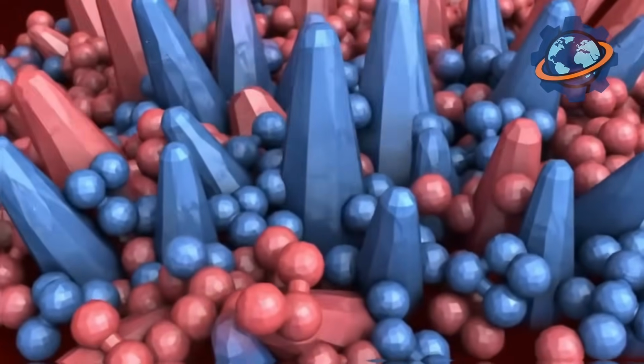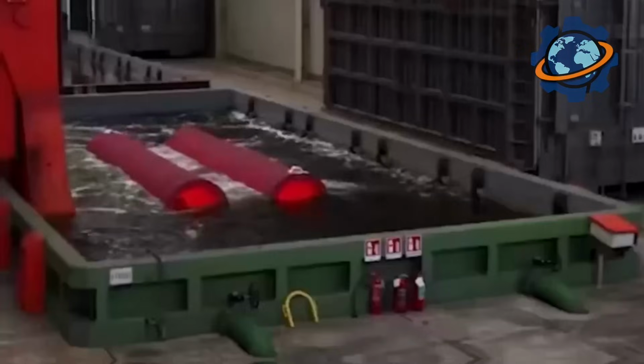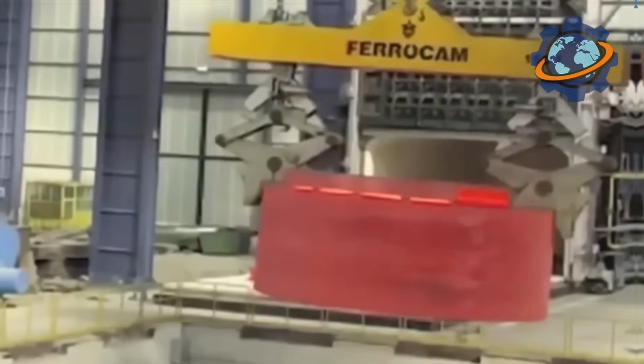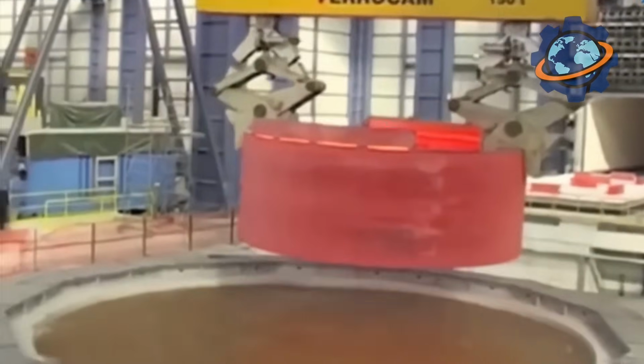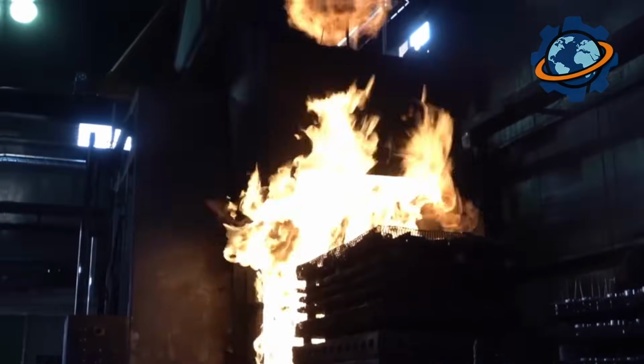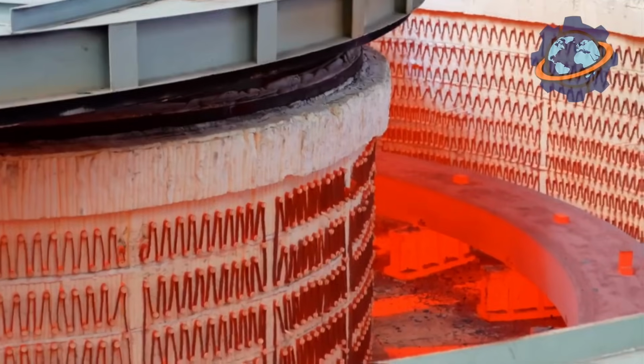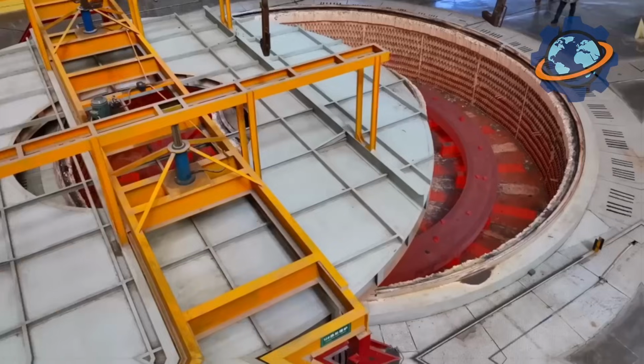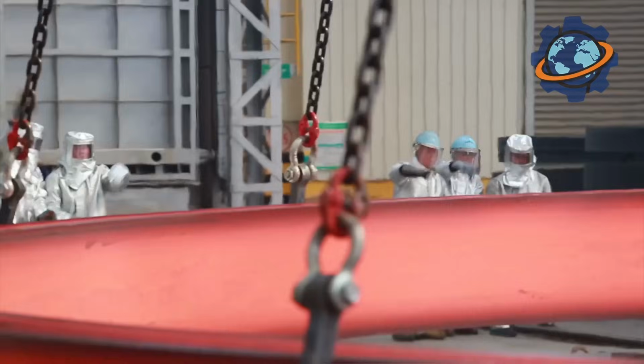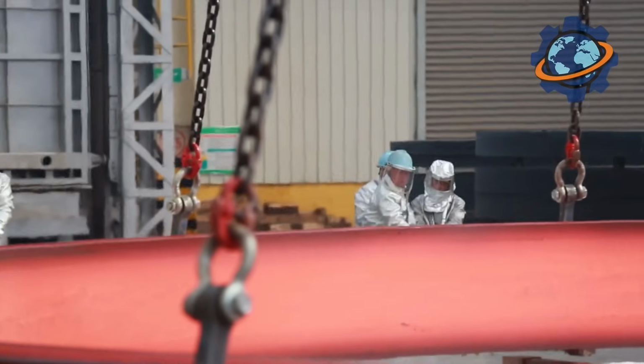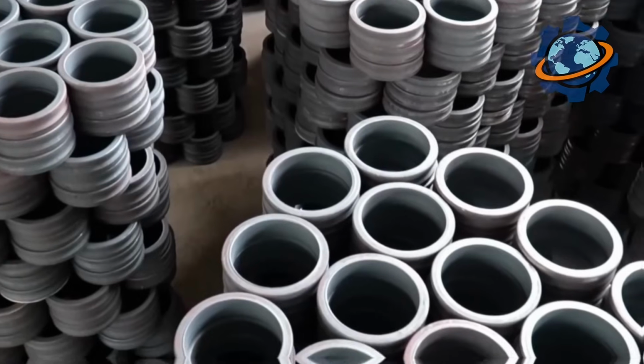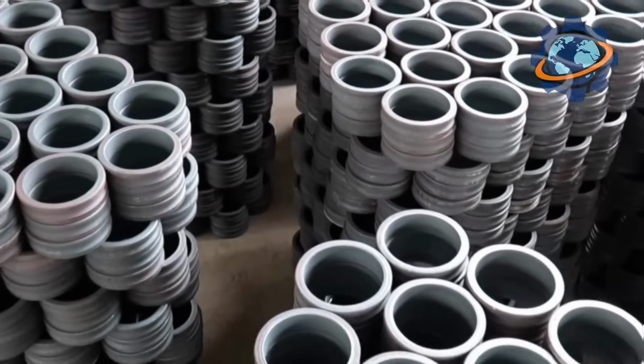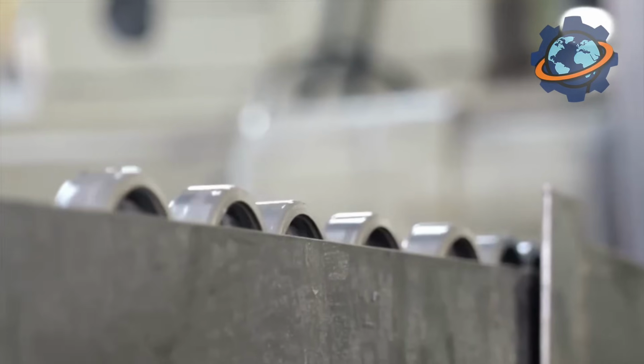But hardened steel has a problem. It's brittle as glass. One hit, and the multi-ton ring could crack. That's why the next step is tempering. The bearing gets heated again, but this time only to 350 to 500 degrees Fahrenheit. It's held at that temperature for 4 to 8 hours, then slowly cooled. Tempering reduces internal stress, makes the steel less brittle, but keeps the hardness.